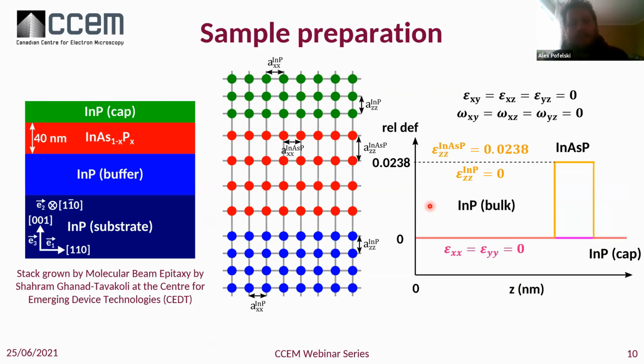So here I am presenting a very simple case, a sample that I will use during the entire presentation and for all the different methods I will be presenting. On the left is the schematic. This is a sample grown by molecular beam epitaxy by Shahram Ghanad-Tavakoli at the CEDT. We have the indium phosphide substrate on which is grown an indium arsenic phosphide layer, and on top an indium phosphide cap layer. This layer in between is roughly 40 nanometers.